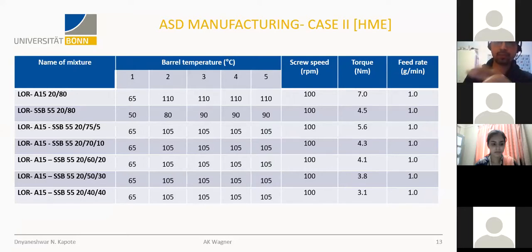We have 5 barrels in it, which stands for 5 heating zones too. The first heating zone was 65 for loratadine and Affinisol, and the rest of the temperature was kept at 110 degrees Celsius, with screw speed at 100 rpm. The torque was 7, and the feed rate was 1 gram per minute. The torque was higher in this case because Affinisol has a higher viscosity. Because of this viscosity, we can observe the torque, and we need a higher shear rate too. While in shellac, we can observe that the torque was low, which was quite expected from its property, because shellac has low molecular weight and is not viscous.